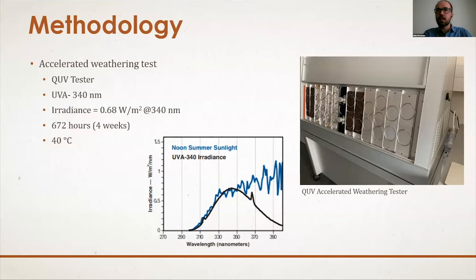First we submitted the samples to UV exposure in the QUV accelerated weathering tester to simulate the damaging effects of sunlight. UVA lamps for a wavelength of 340 nanometers were employed, corresponding to an irradiance of more or less 0.68 watt per square meter, which is equivalent to noon summer sunlight. And this makes it possible to obtain quick results without sacrificing the correlation. So the samples were exposed during 4 weeks, in a total of 672 hours at 40 degrees Celsius. These lamps were selected because they make it possible to realistically reproduce the damaging effects of sunlight that can occur between 300 and 400 nanometers, which typically causes the most weathering damage to materials exposed outdoors.